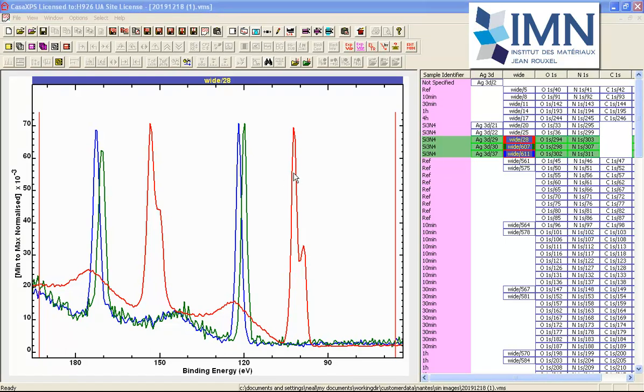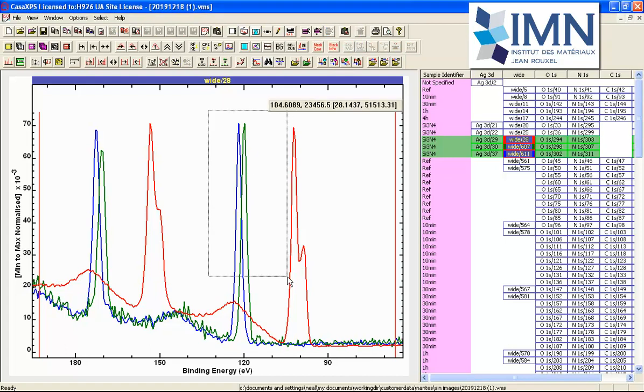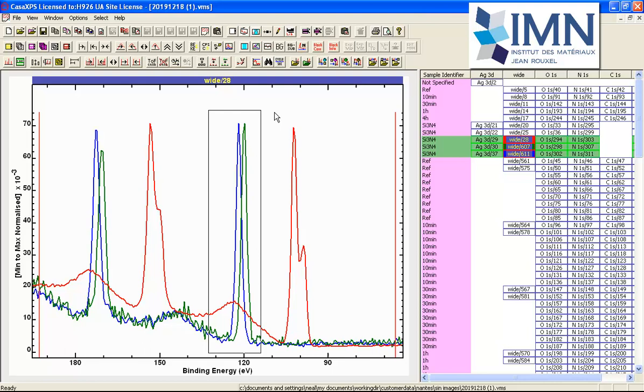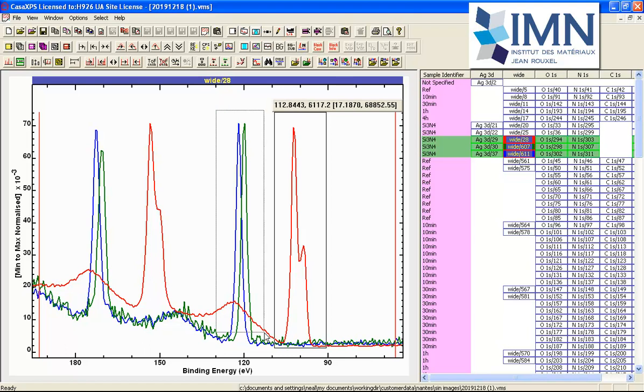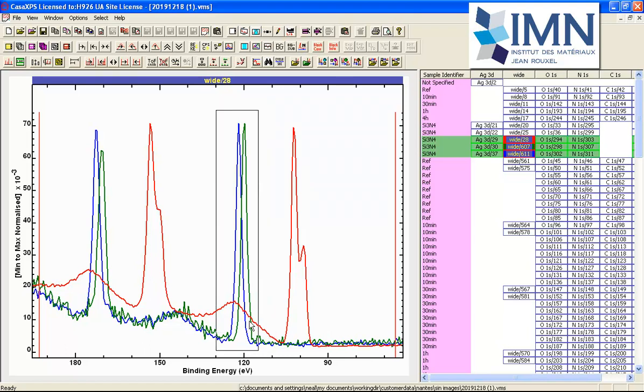The one that has charge compensation compared to the two without is different because this one is measured at pass energy 80 with a full slot, whereas these two were measured using pass energy 160 and a 55 micron selected area aperture. The analysis area of the sample for these two peaks is very much smaller than the analysis area here, which is about 300 by 800 microns. These two have been measured using a 55 micron aperture and a higher pass energy, so in principle that should give more signal.